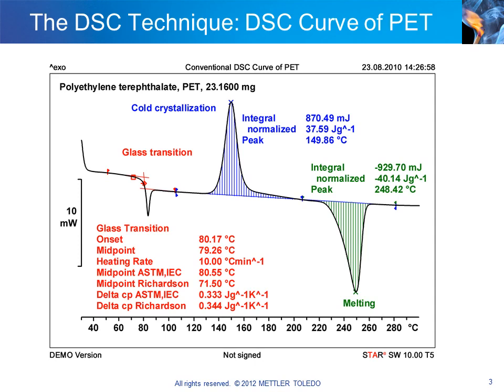Between the glass transition and melting, very small crystallites first form as the sample is heated. With increasing temperature, these crystallites gradually change to more stable crystals. Unfortunately, we see nothing of this reorganization process in the DSC curve because the exothermic and endothermic processes occur simultaneously. In fact, many materials, especially polymers, exhibit thermal events that depend on the DSC measurement conditions. This is because the materials undergo different reorganization processes. I will now explain this in more detail.